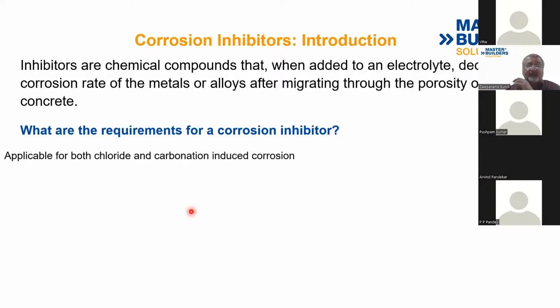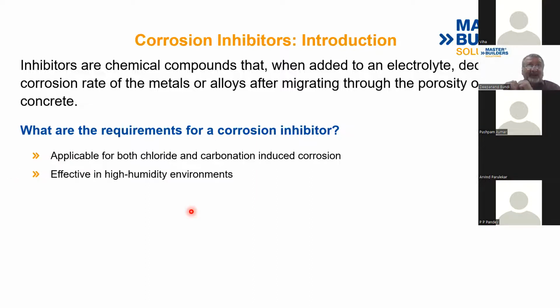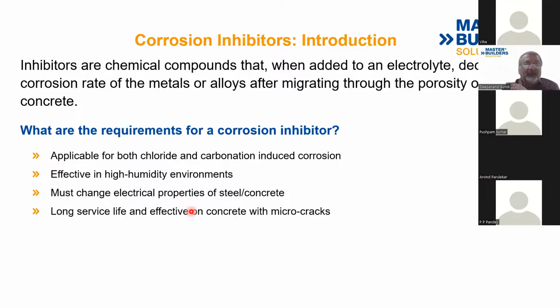You should be able to control both, as I said, corrosion due to chlorides and corrosion due to carbonation. It should be effective in good humidity areas. India per se is a good humid area. If you talk about it, we have a good coastline. It should change the electrical properties of the steel. That means the I-corr value should be in control and very low. The current passing through it should have a good service life